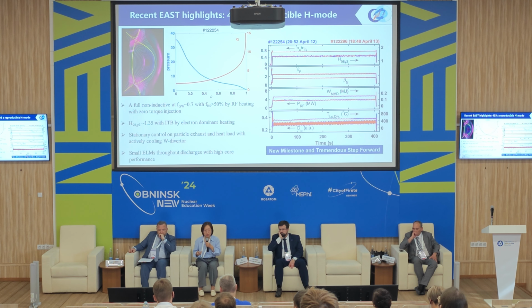Here I show you the new record we achieved last year. That is the 403 seconds reproducible H-mode operation. You can see the time traces of the plasma parameters on the right. This is a full non-inductive plasma operation with the density, Greenwald density fraction about 0.7. And the bootstrap current fraction is larger than 50% by the RF heating injection with zero torque.